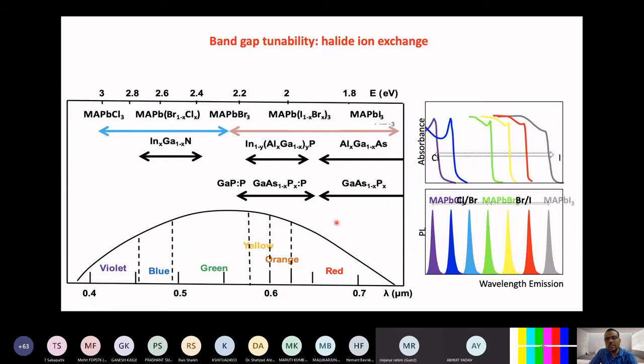Further, as I was telling, you all have seen in your daily life that you can get different colors of LEDs: red, green, blue, orange. Why? How does it happen? Generally, if I go with an inorganic semiconductor like gallium phosphide or gallium nitride or gallium arsenide, in gallium arsenide, by adding aluminum, you increase the band gap, because aluminum is small in size as compared to gallium, so your lattice constant goes down, and when the lattice constant goes down, the band gap increases.